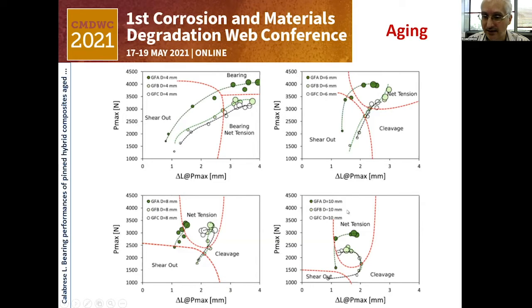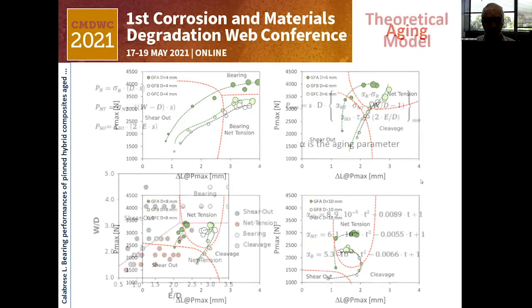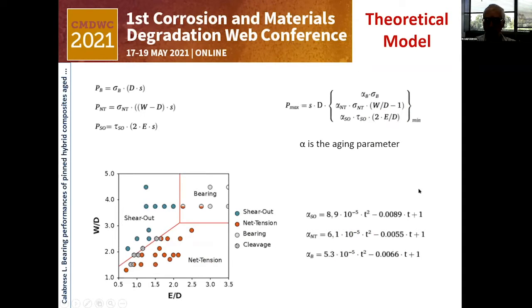And instead, for large diameter, the really premature fracture due to net tension switches the behavior of the composite like in the bearing configuration, with mainly a reduction of the load, but with no significant shift toward higher displacement. Then we should talk about the behavior, but at this point, also due to aging, we observe this typical trend. But at this point, we tried to identify the failure mechanism and to relate this failure mechanism to the aging.